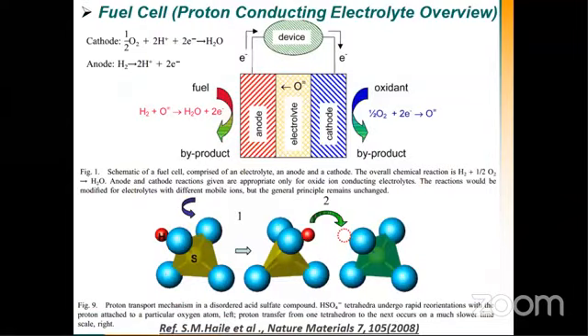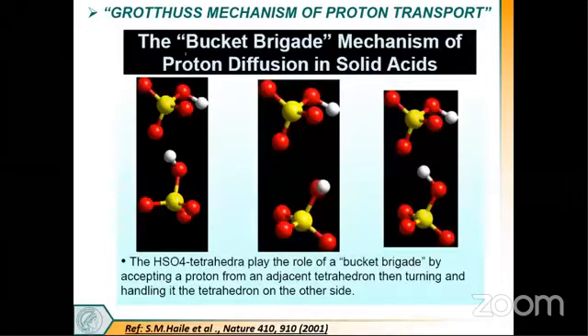In the bucket brigade mechanism, the rotor molecules, which are SO3H based sulfonic acid based molecules, rotate at a certain triggering temperature. I will explain the triggering temperature of these molecules. At this triggering temperature, the sulfonate atoms move in such a way that it allows the proton to pass through the channels of the membrane. The difference between vehicular and bucket brigade mechanism is that the rotation allows the proton to pass through one by one through the neighbors. And in the vehicular mechanism, it's like loading a car with a proton and allowing it to pass through the channel. So these are different mechanisms explained in various papers.